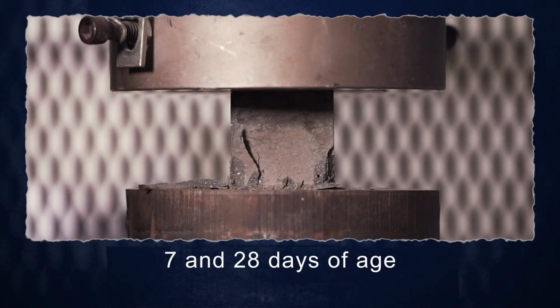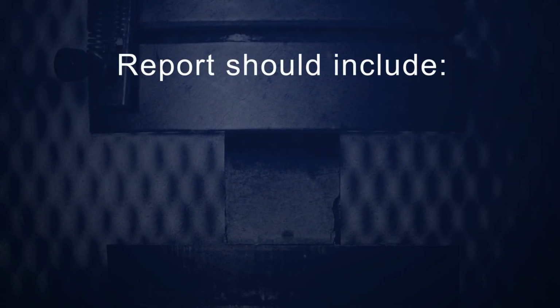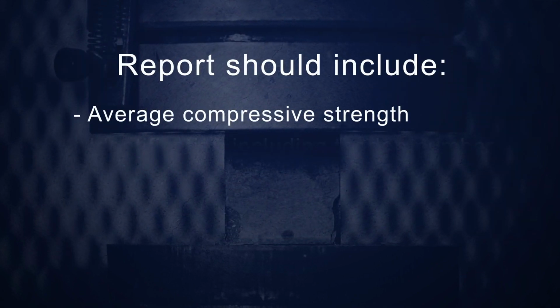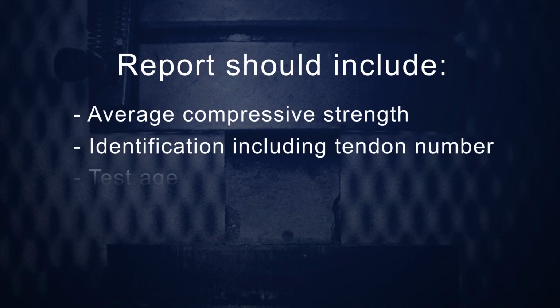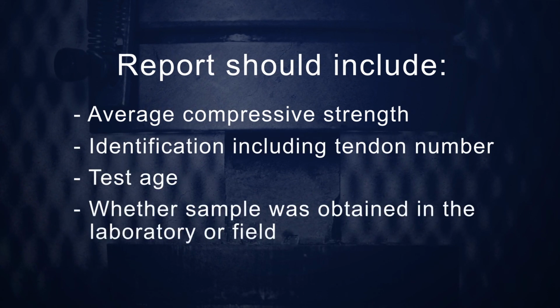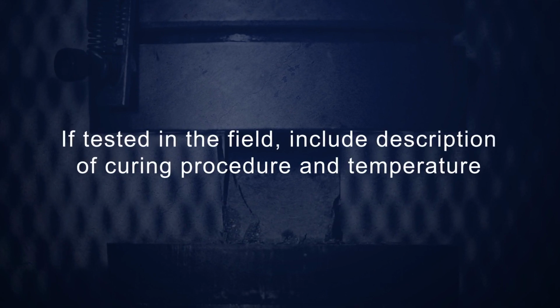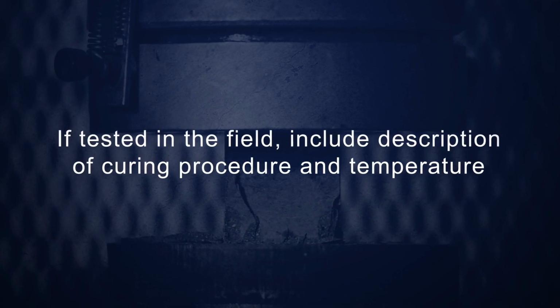Tests should be calculated at 7 and 28 days of age unless otherwise required. Report should include average compressive strength, identification including tendon number, test age, and whether sample was obtained in the laboratory or field. If tested in the field, include description of curing procedure and temperature.